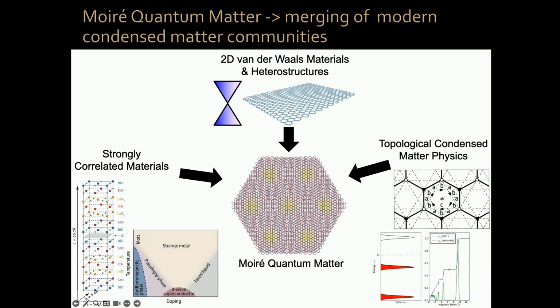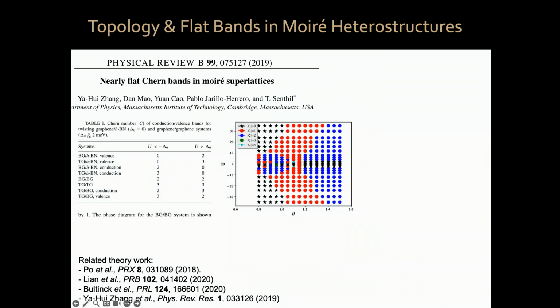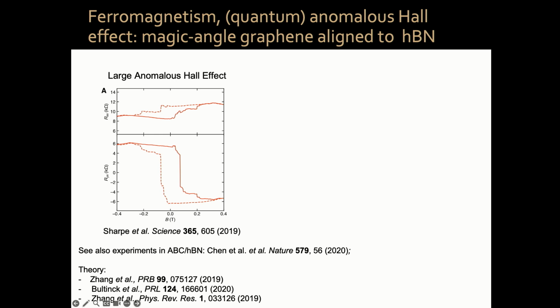So the fact that topology would play an important role, there were early theoretical works about magic angle twisted bilayer graphene, and then my collaborator Senthil at MIT, we published a paper. We already suggested that there would be all these nearly flat Chern bands in Moiré superlattices, different types with different Chern numbers, etc. And just about 6 months later, the group of David Goldhaber-Gordon at Stanford measured a very large anomalous Hall effect. So a Hall effect, finite Rxy at zero magnetic field in magic angle twisted bilayer graphene aligned to HBN. It's sort of a double Moiré heterostructure.